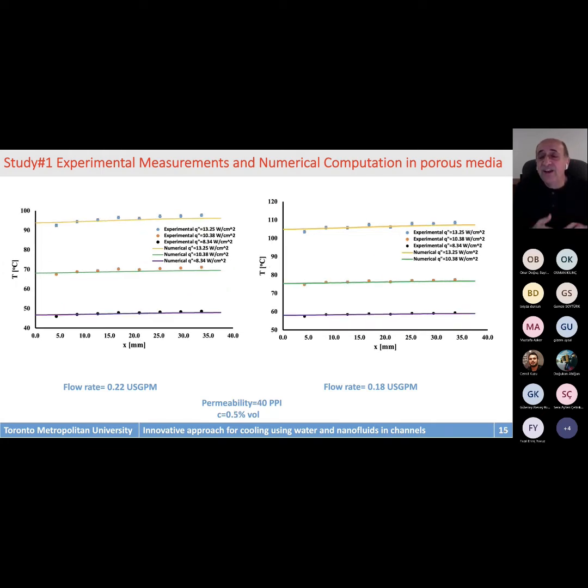And also we did it for a variety of nanofluid nanoparticle concentrations between 0.1% volume to 0.5% volume. And one thing you need to remember is when you use nanofluid in your flow, when you finish your experiment in a single day, you must clean the system. If you don't clean your system and the porous block which you are using, we will have some blockage, and the nanoparticles will be very difficult to remove from this blockage of porous material. So this is something you need to take into consideration in your experimental work.